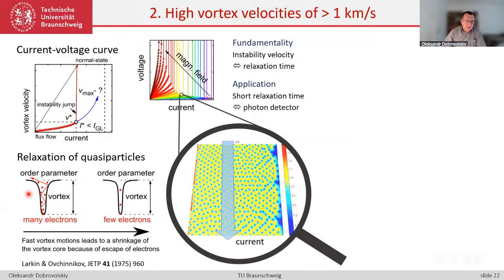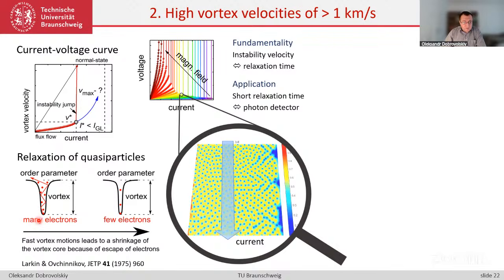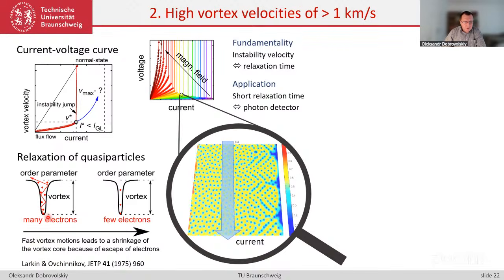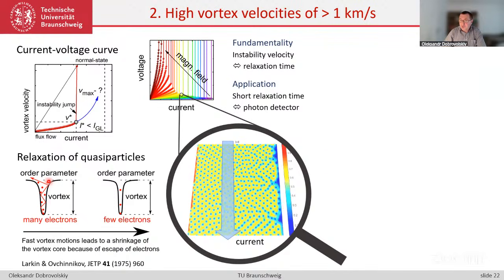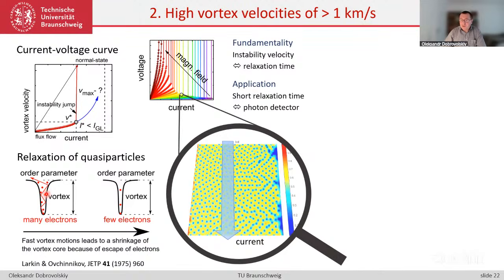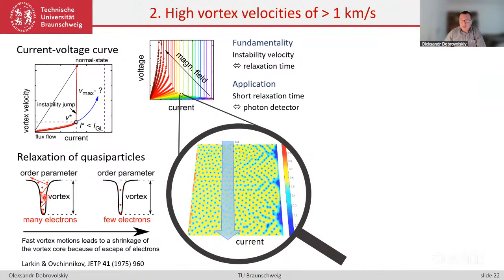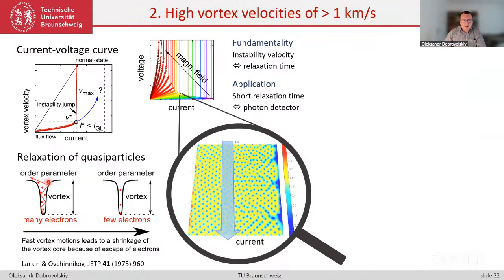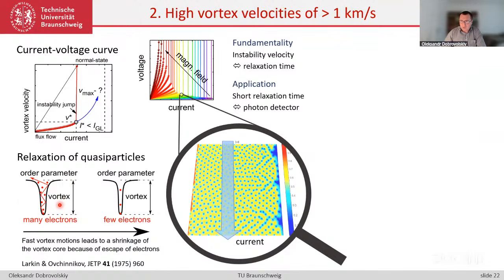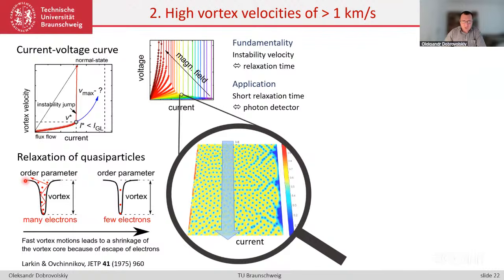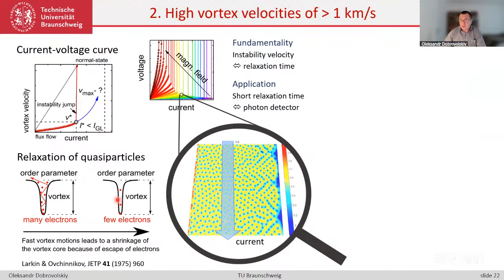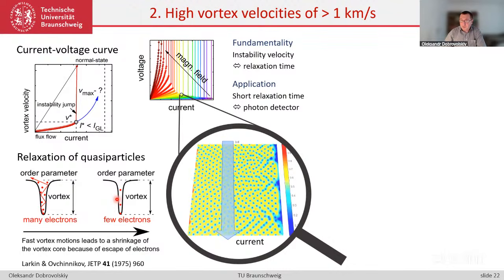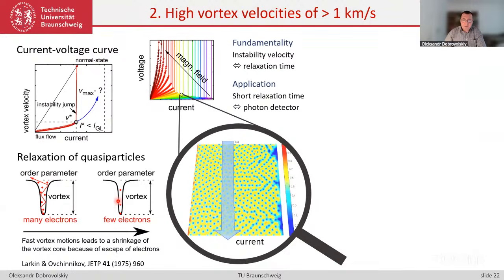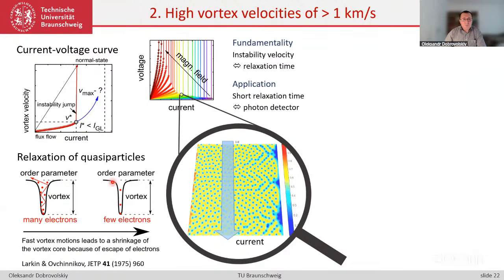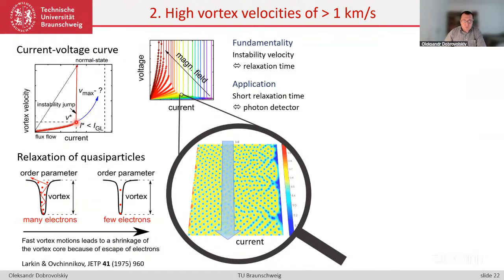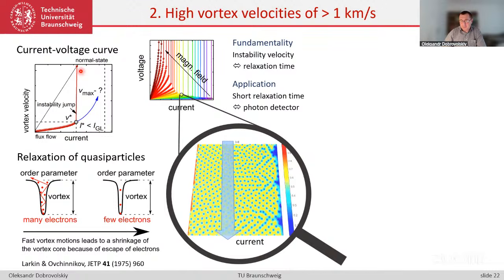And the microscopic reason for that is the phenomenon called flux flow instability, described theoretically by Larkin and Ovchinnikov. The idea is that the vortex core contains unpaired electrons, and for these electrons, these very high velocities mean that they acquire kinetic energy comparable with the potential energy variation at the vortex core and around it. So these electrons can escape from the vortex core, and the vortex core shrinks. And while driven by the same transport current, a narrow vortex can then be accelerated faster and faster. It's a kind of positive feedback. That means avalanche-like acceleration of vortices leads to abrupt destruction of the superconducting state.